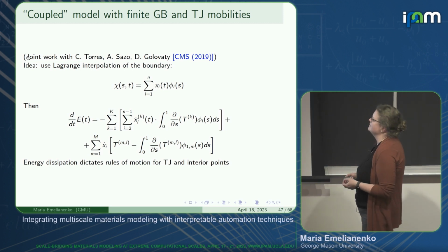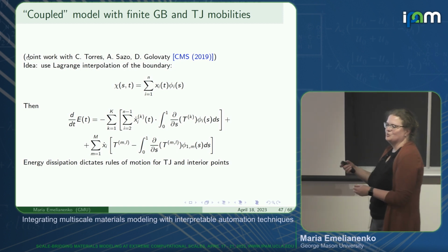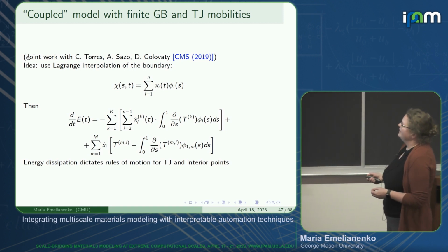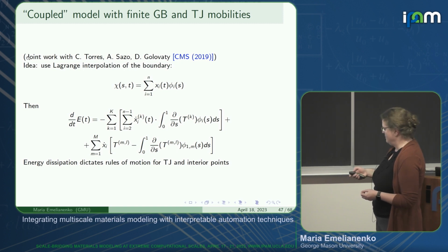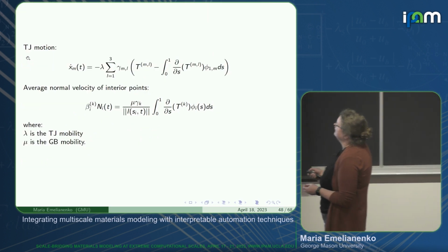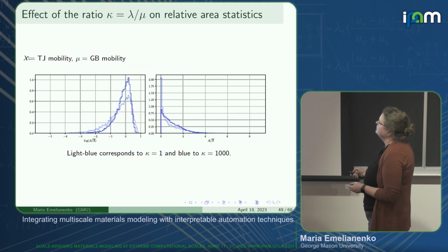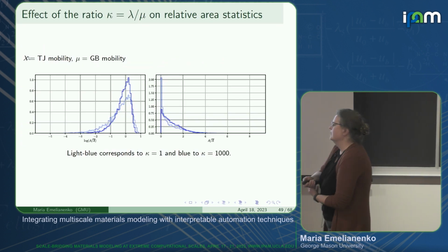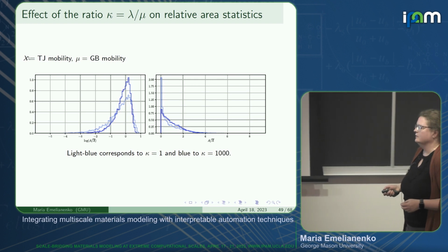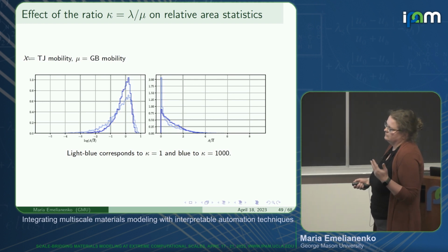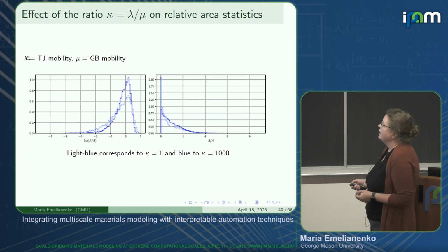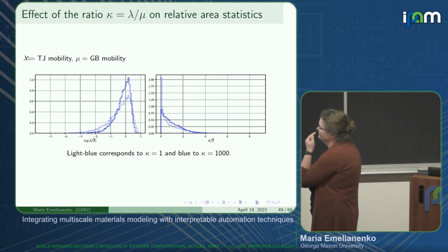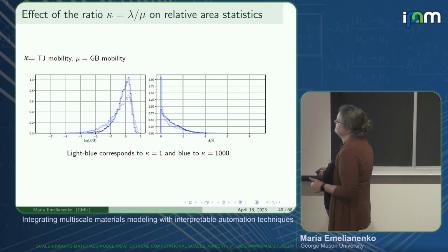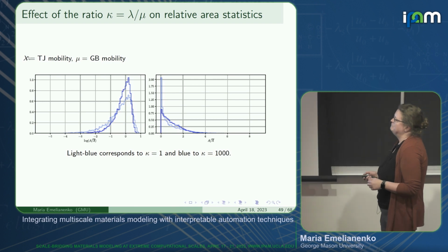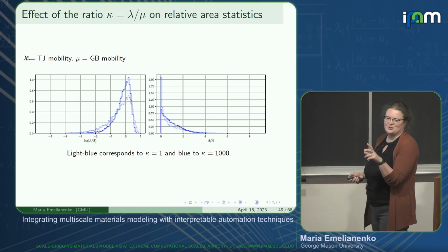And then you have flexibility to choose the ratio between the two mobilities of the boundaries versus triple junctions. And so this was the Lagrange interpolation type of idea that Claudio Torres and his students have developed recently. And so you can basically implement these codes, and you can run large-scale simulations with a lot of grains. What you see is that there is an effect of this ratio, as I said, right? So this ratio kappa is the mobility of the triple junction versus the boundary.